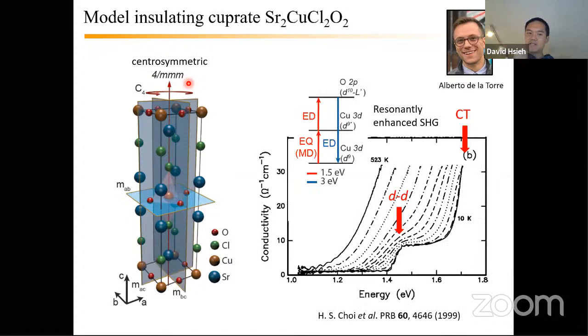The SHG from this material is very weak, as I'll show you in a slide, but what we've done is we've managed to pick up an SHG signal nonetheless by leveraging a resonant enhancement process. Okay, and that resonant enhancement process involves having an intermediate state. Your incident photon energy is on resonance with a dd transition, and then your second photon for SHG goes from here to the charge transfer gap edge. And so you have this sort of double resonance that allows us, I think, to pick up the SHG, even though generically it's quite weak.